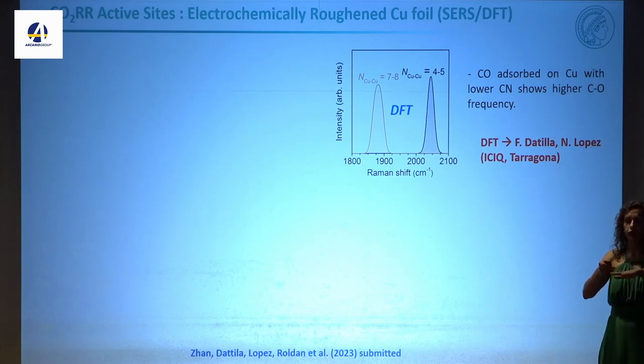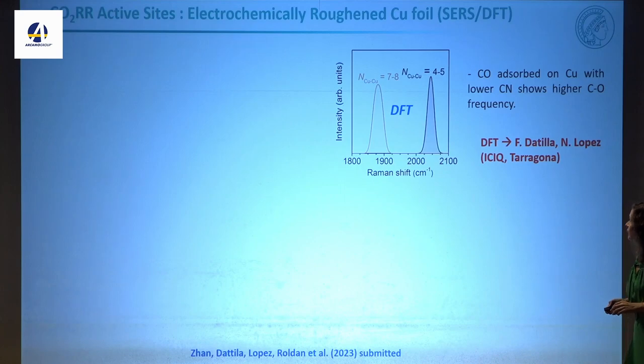My surfaces don't have only bulk coordinated atoms. Normally, under reaction conditions, you even see the formation of clusters on the surface. We have microscopy data for that. That means even on a single crystal, you create clusters and low coordinated sites under reaction conditions. And this affects the coordination number of copper that normally should be 12, could be 7 to 8, could be smaller, and this causes a very large Raman shift. So this is very nice because we can associate this to what we are seeing in our experiments.